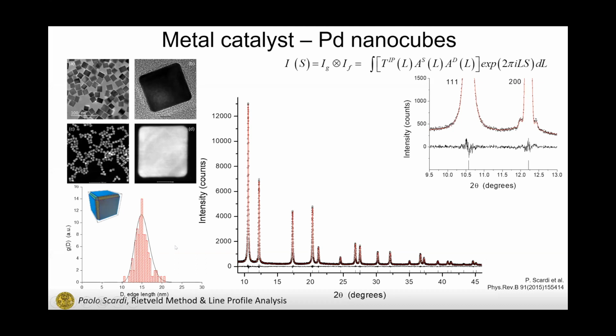identical with the TEM. This is quite a remarkable result, and is only possible because the shapes are so nicely identical. And in this case, what you see by electron microscopy and what you see by diffraction is identical, which is of course not always the case. Here, grains are crystallites. This is not always the case.